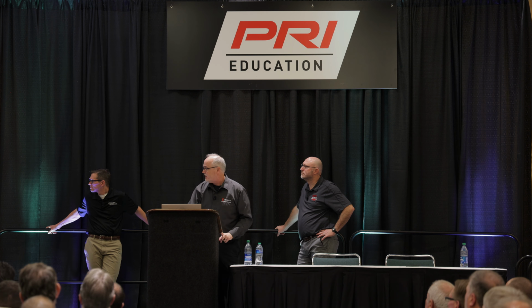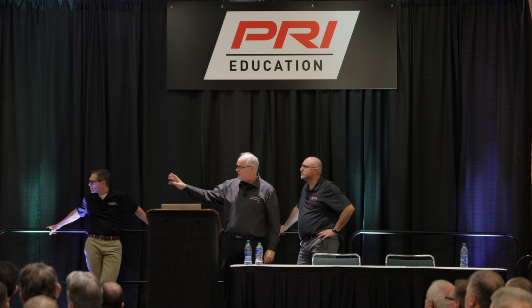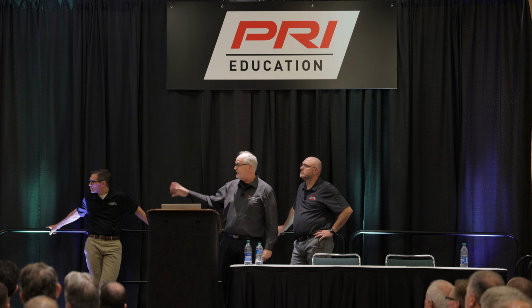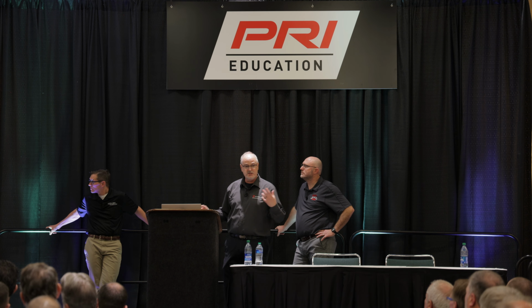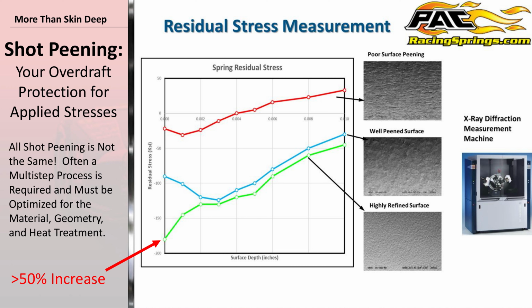Sometimes we do some damage to the surface, so what they'll do is come back with a shot peen. They'll polish it and then come back in shot peening, and they can create this double compressive surface. So if you imagine this plot over here, and this was all done with the X-ray diffraction machine. If you want to be really good at peening, you wind up having to buy one of these X-ray diffractions to measure this hardness, this residual stress in there.